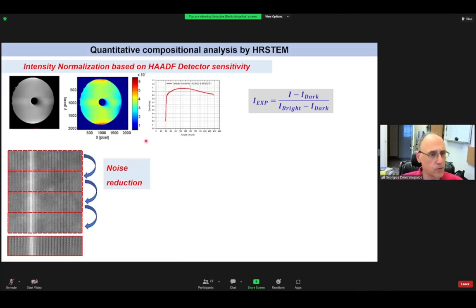Another thing that we need to do is noise reduction. And high resolution STEM images are, by nature, quite noisy, even if they are obtained with probe corrected microscopes. So there are ways to do noise reduction. Mainly, you have to do it without tampering with the actual intensity that you are recording. You have to be very careful on how to do noise reduction. And one way that is very commonly used is the overlapping of multiple images.